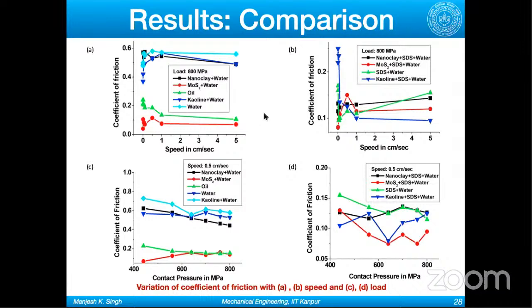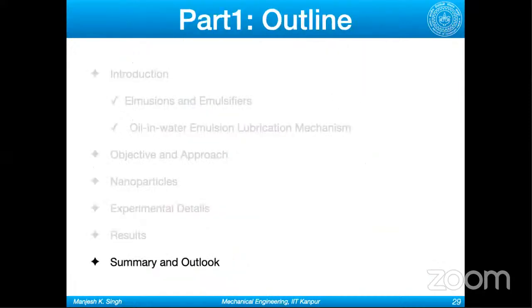But when we added the SDS, the performance also improved, but we are not sure exactly if it is because of kaolin or nanoclay or just because of SDS. But we can certainly conclude that MoS2 plus water gives us a coefficient of friction which is comparable to or even lower than with just oil for lubrication. So this could be one possible option. I'm not saying that you should right away use it, but we need to probe it further, as it seems to be a good candidate to replace oil in water emulsions for lubrication in metalworking.